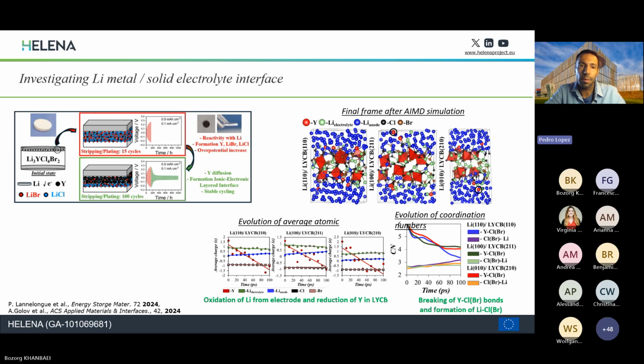We have observed with the experimental characterization tools that there is a formation at this interface of different lithium salt species, such as lithium bromide and lithium chloride, as well as yttrium metal. And so thanks to these computational tools, we were able to understand that this is an intricate and dynamic layer in which these elements are combined in different layers, with isolating layers, sorry, of lithium bromide and lithium chloride, and an electronic conductive layer of yttrium.